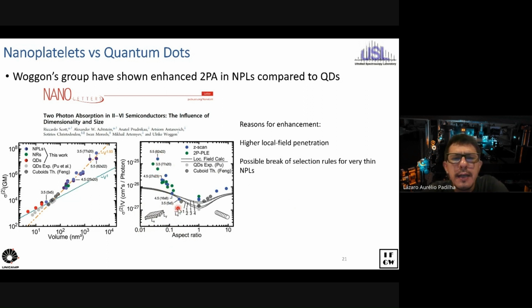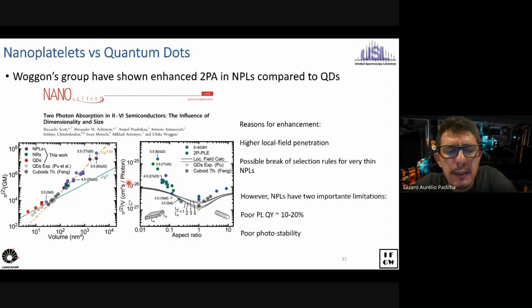And their argument for that is basically because this is what you would get simply by increasing the local field penetration, and that's what they get experimentally. But you can get this, and that's all fine, but there's one problem with that. When you go to nanoplatelets, for example, you get poor quantum yield, on the order of 10 to 20%. On the other hand, you get poor photostability also. Nothing is as stable as those nice little spherical nanomaterials.